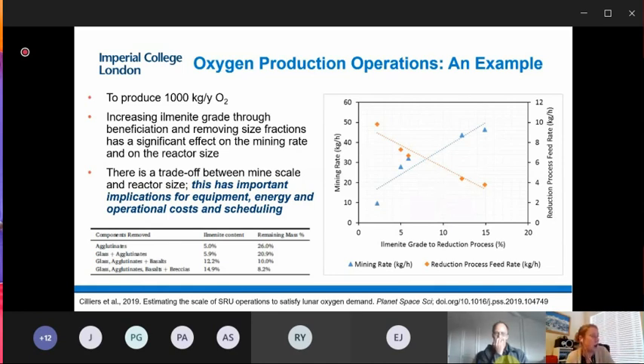So we took our feed, our regolith, and we said, well, if we take out the agglutinates, and then we take out the glasses, and then we keep stripping away different components, what happens to the ilmenite content? If we take out the agglutinates, then our ilmenite increases to 5%. If we take out all the glasses, the agglutinates, the basalts, the breccias, then our ilmenite content increases to just short of 15%. So by stripping away different components, theoretically, we can increase the proportion of ilmenite, and this correspondingly reduces the mass in our feed going into the reactor.